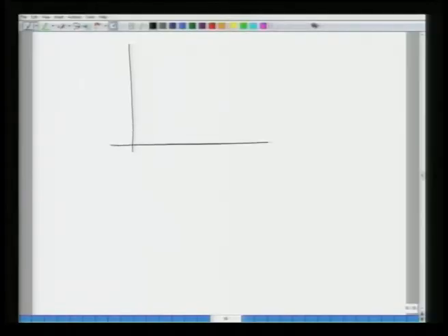So when you plot the vacancy concentration as a function of 1 by T, N would mean basically the V_Na concentration. The intrinsic vacancy concentration varies like this as a function of temperature, and this slope will be equal to delta H_S star divided by 2k.